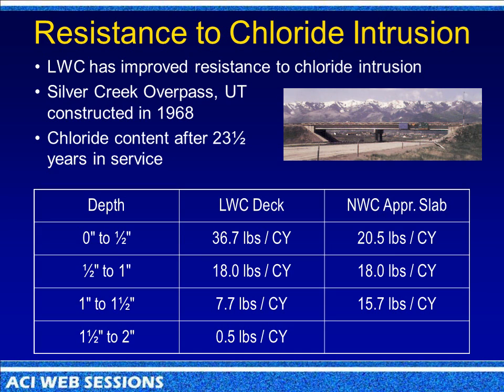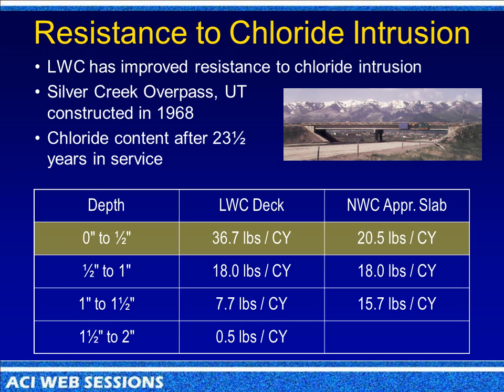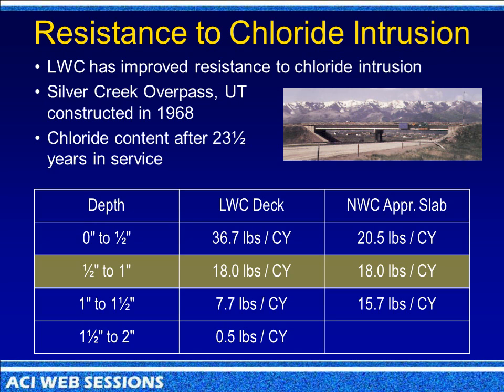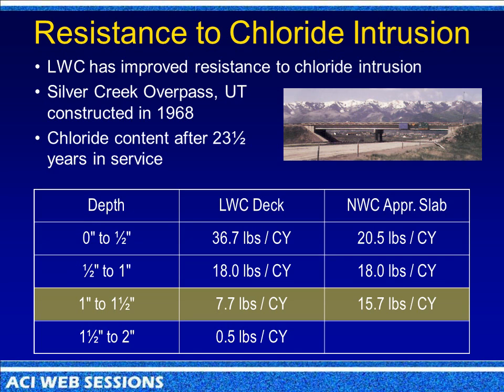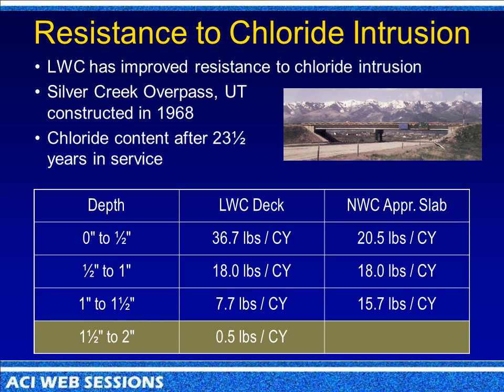Now here's a real world situation. This deck has been in for 23 years. It was removed because of the Olympics, and they needed a lot more traffic out there in Salt Lake City. But this is salted very heavily, and you can see at that first line, the chloride penetration was a lot more for the lightweight, but at the second half inch, it was equal. And in the second half inch after that, the third half inch, the lightweight was half. And then it got very low, and why they didn't have one for the normal weight, I don't know. But you can see in the real world, this really does shut down the chloride intrusion.